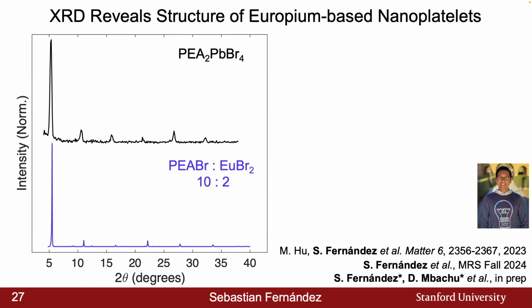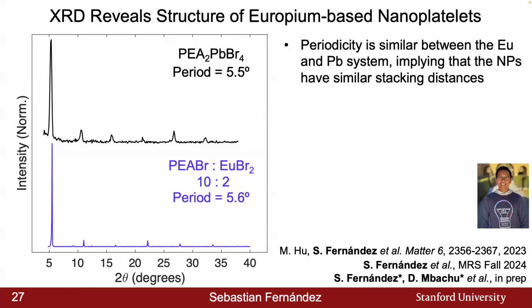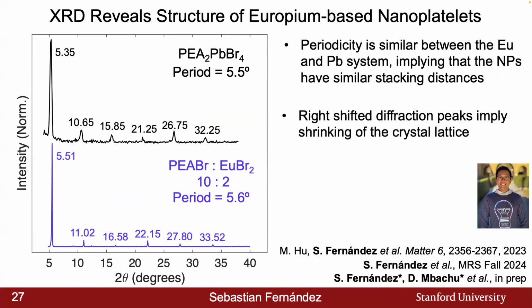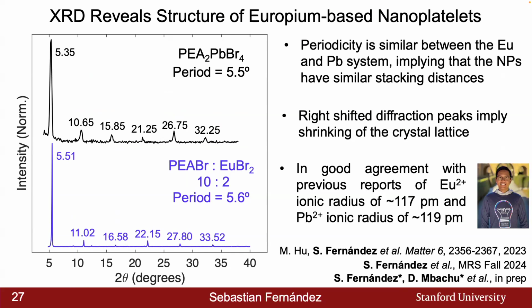And we can see some striking similarities. The first is that the periodicity between the diffraction peaks is quite similar, implying that these nanoplatelets have similar stacking distances, which should make sense because we have identical ligand species in this case. When we annotate the diffraction peaks, we can see that in general this europium-based material is right-shifted for all of the peaks compared to the material up top. This is in good agreement with previous reports of the ionic radii of europium and lead, where europium is known to have an ionic radius a little bit smaller than lead. This suggests that we're actually forming phenethylammonium europium bromide, because it is quite similar to the phenethylammonium lead bromide.